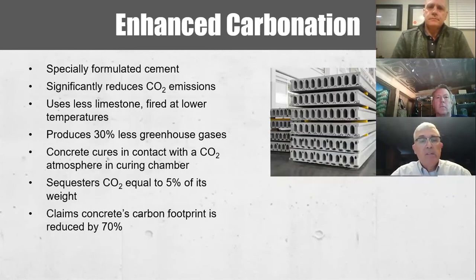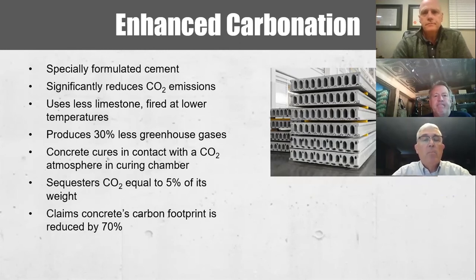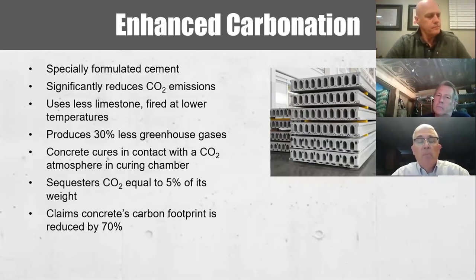Another example of enhanced carbonation is the use of specially formulated cement. This cement is manufactured in a process that uses less limestone, and in the calcining process, they're firing the kilns to manufacture the cement at lower temperatures. The developers of this process indicate that that results in 30% less greenhouse gas emitted during the manufacturing of this specially formulated cement. And then that cement is used to manufacture concrete products, right now in the precast industry primarily. So you manufacture your precast components and then move them into curing chambers that have a CO2 rich environment.